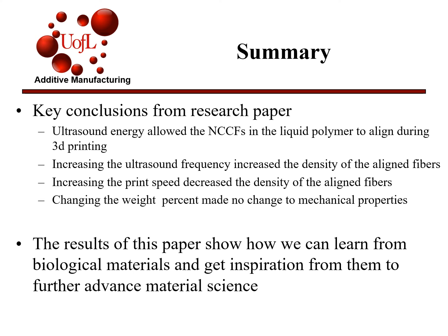Another key conclusion is that the print speed actually decreases this density and makes it harder to align these fibers, but a lot of this can be overcome through the introduction of this ultrasound energy. And another key conclusion is that changing the weight percent or the amount of the microfibers within the polymer really has no effect on a lot of properties. It's the alignment of the fibers that is much more important.